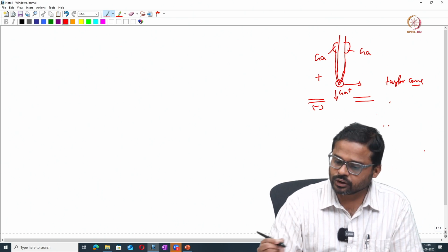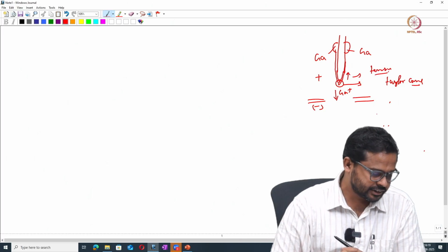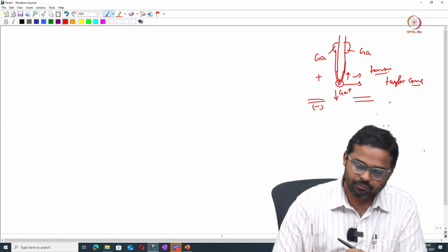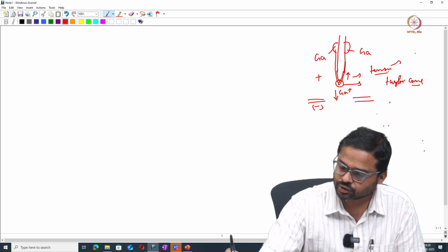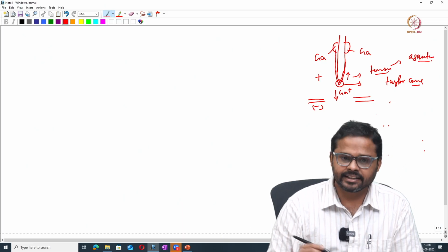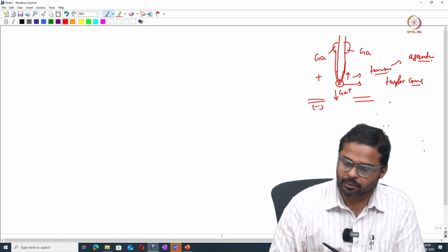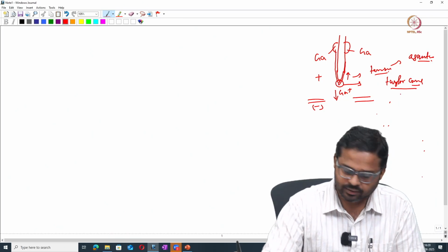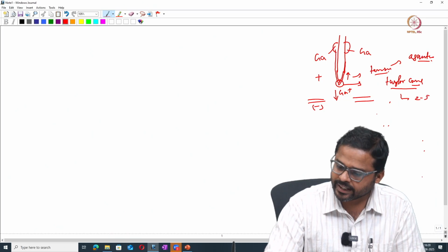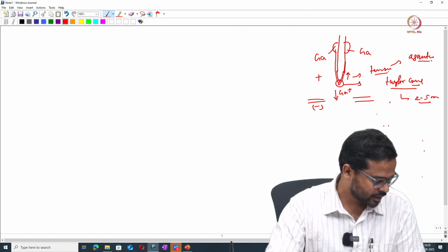There is also an opposite force, due to the surface tension in the liquid gallium, that acts against the electrostatic force, and when they balance together, there will be a formation of a Taylor cone, which is around 2 to 10 nanometers, or 5 nanometers, in tip